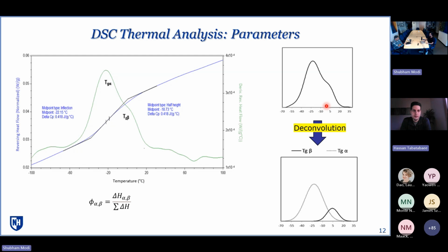Thank you, Shubham. Maybe I can also add a couple of additional contextual comments. If folks look at the blue line on the left-hand side, that is the normal glass transition type of curve most folks would see when they run a DSC test. Just looking at that, it does seem like you have a single broad transition, which is what most often is attributed to the asphalt binder. The reason we go to that first derivative, as Shubham said, is because it allows us to analyze what is happening at the glass transition region at a much more detailed level.